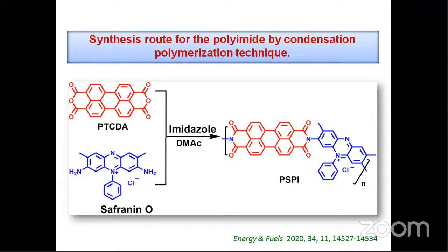Here, the perylene tetracarboxylic dianhydride reacts with the safranine O group under nitrogen atmosphere at 150 degrees centigrade using imidazole and dimethylacetamide as a solvent to give this conjugated polyimide. Here, this perylene diimide acts as an electron accepting unit, whereas the safranine moiety acts as an electron donating unit. Now, this synthesized polyimide has been characterized by various spectral, optical, electro-optical, and thermal techniques.